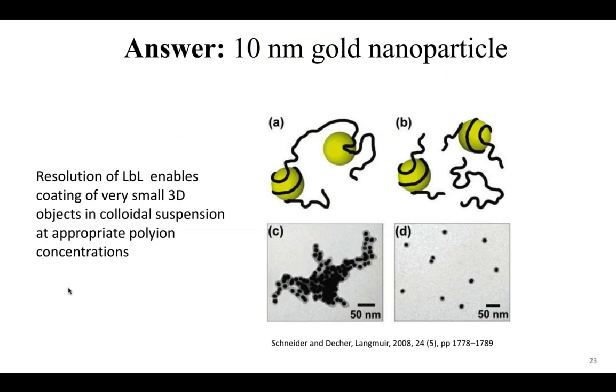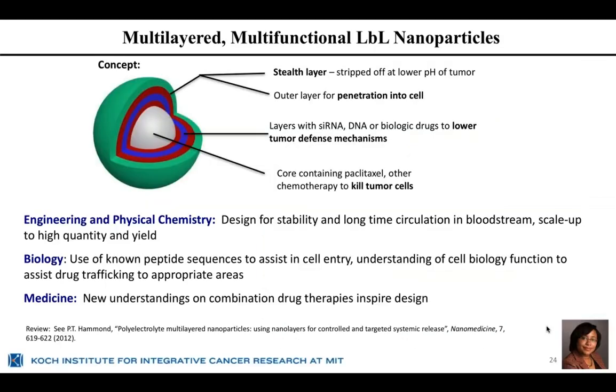And I'm taking this image here just to give you an idea of this resolution from one of the papers by Schneider and Decher from 2008, in which they actually talk about the conditions which allow these polyelectrolytes to wrap around nanoparticles based on the hydrodynamic size and the degree of extension of these chains. Clearly, it's going to be sensitive to things like pH and ionic strength.